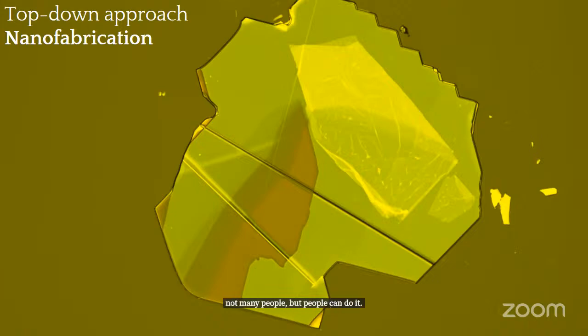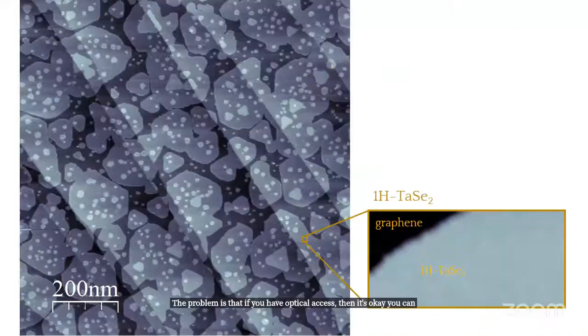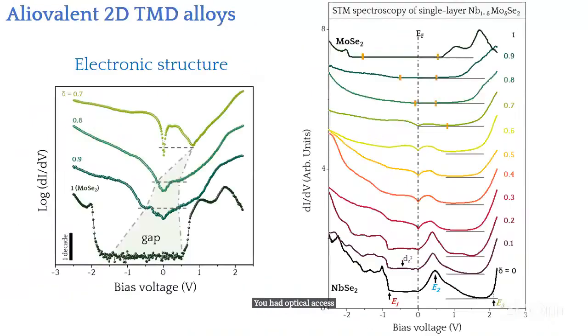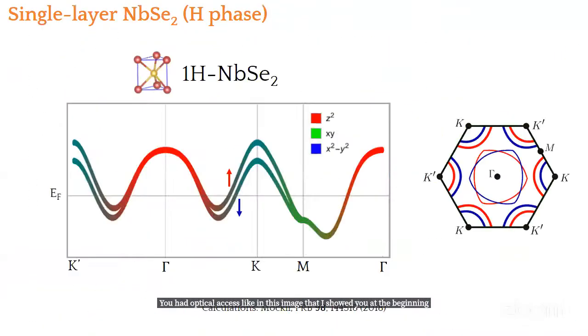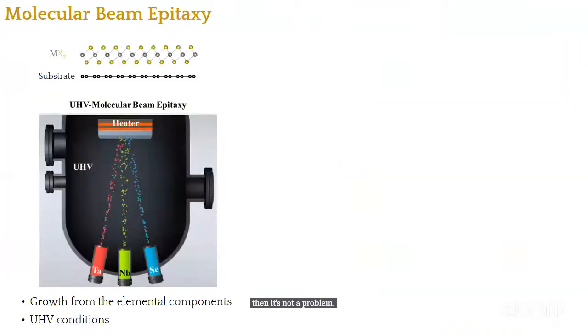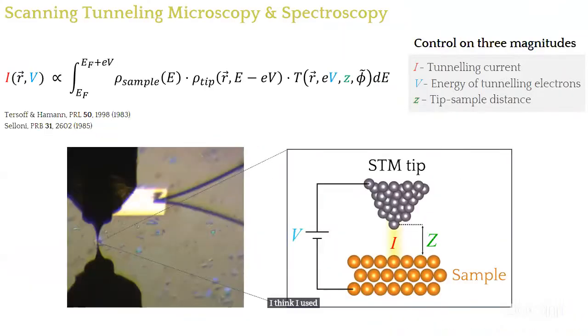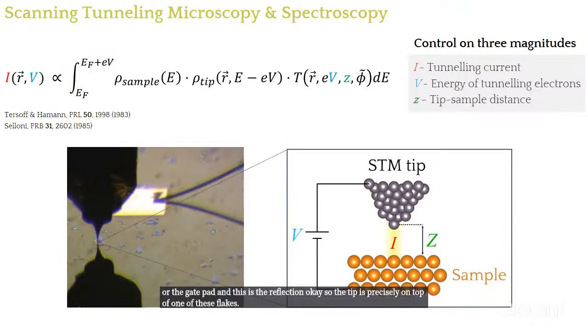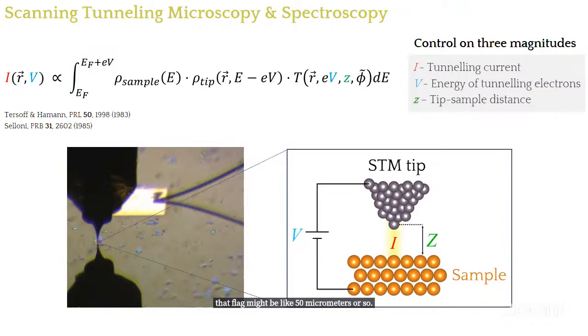The problem is that if you have optical access, then it's okay. If you have optical access, like in this image that I showed you at the beginning, then it's not a problem. So this is the surface. These are some crystalline, micrometer size crystals. And this is the tip. This is the bias pad or the gate pad. And this is the reflection. So the tip is precisely on top of one of these flakes. That flake might be like 50 micrometers or so. If you have optical access, you can precisely move the tip. Otherwise, you have to rely on this capacitive imaging.